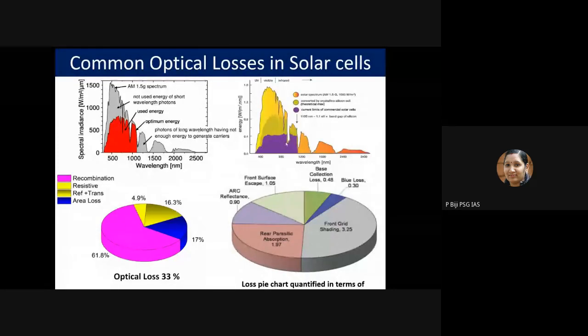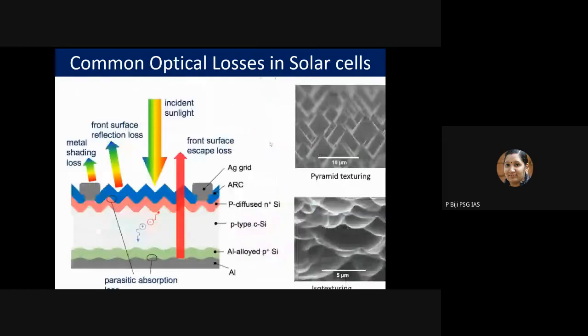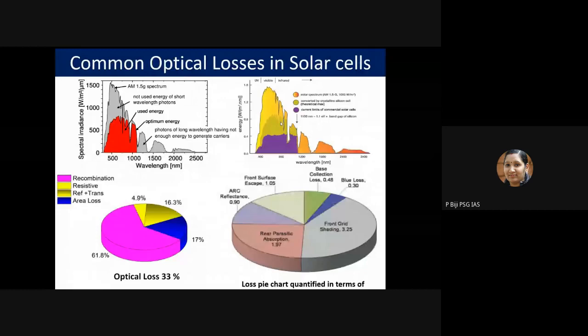So when you see the commercial solar cells coming around 23 or 20%, you are not actually getting the benefit of the entire spectrum shown in this red region. But actually, what you are getting is this purple color, which I have shown in the second spectra. So that's the current limit of commercial solar cells. You are not getting the entire spectrum available by the theoretical maximum. So you are getting a partial energy only.